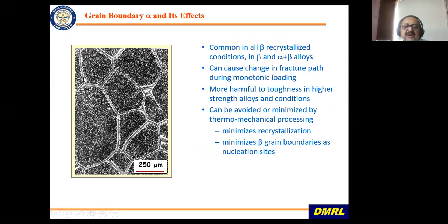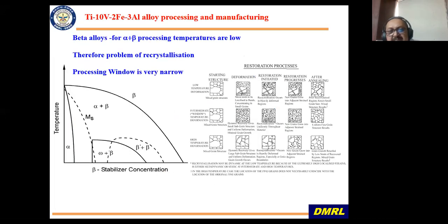So as I told you, in case of beta alloys, you have to be more careful about the grain boundary alpha, because there is too much of strength difference. Inside the grain, the strength is high, and around the grain boundary, it is less. So you cannot allow grain boundary alpha precipitation. This is a point of concern, and there are processing routes to minimize grain boundary alpha precipitation.